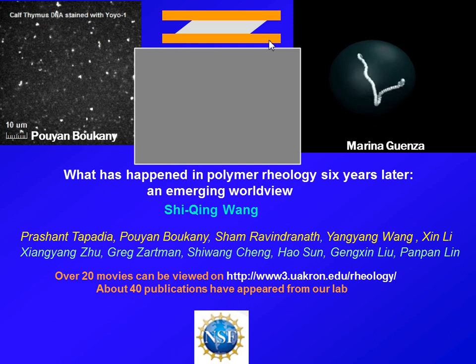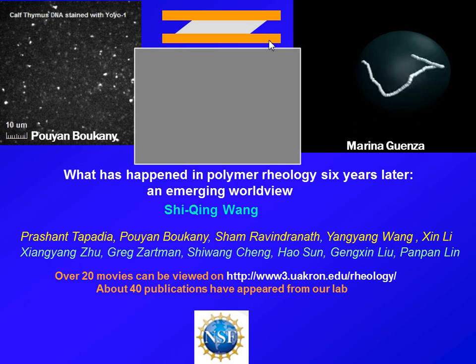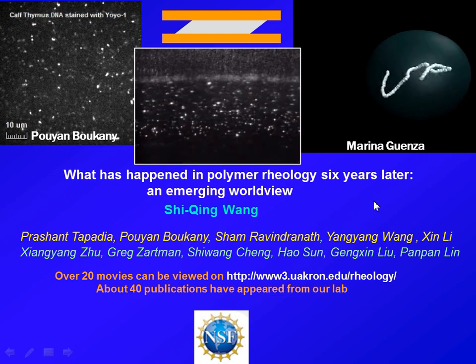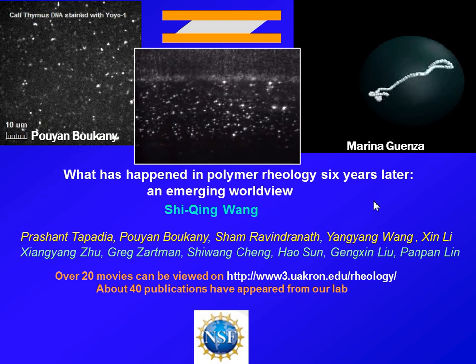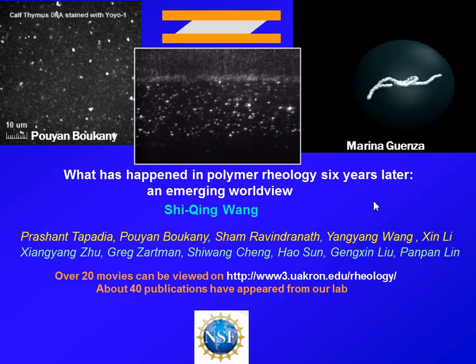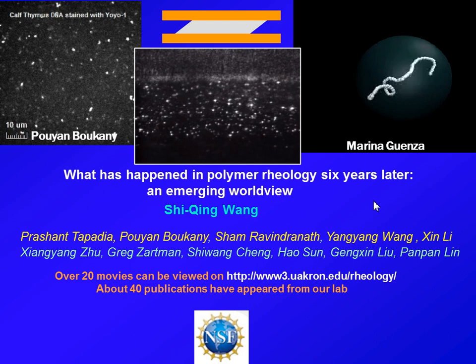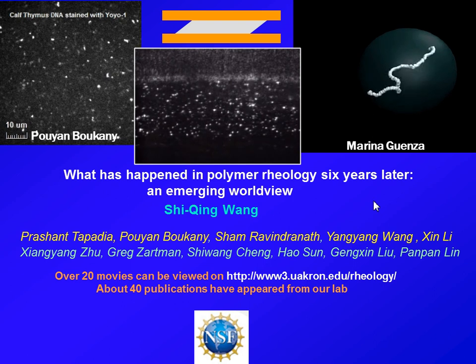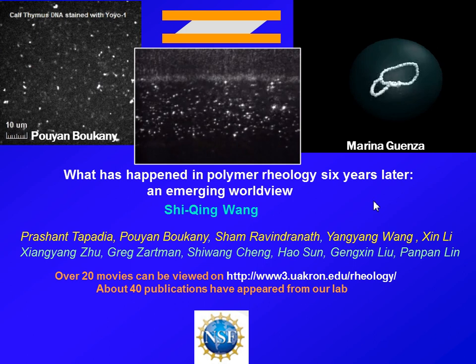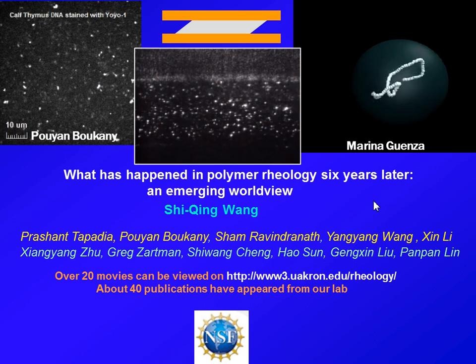You make a step strain. People have conducted this kind of experiment for many decades. The perception is that after a step strain, you ought to see nothing microscopically. It should be quiet, quiescent, nothing should be observable. That view got completely changed about 6 years ago at APS in Baltimore, where this type of movie was shown for the first time. After step strain, we see motion, a tremendous amount of microscopic motion taking place. You watch it again, after a step strain of 300%, it has motion.